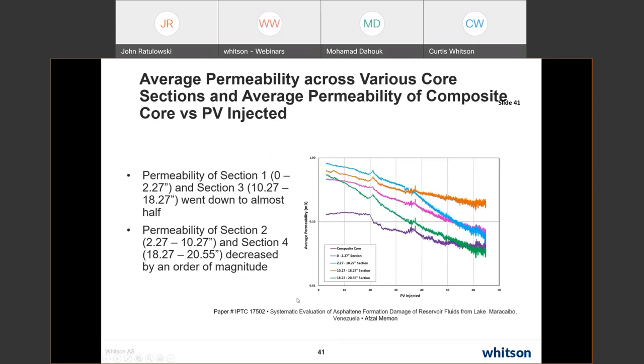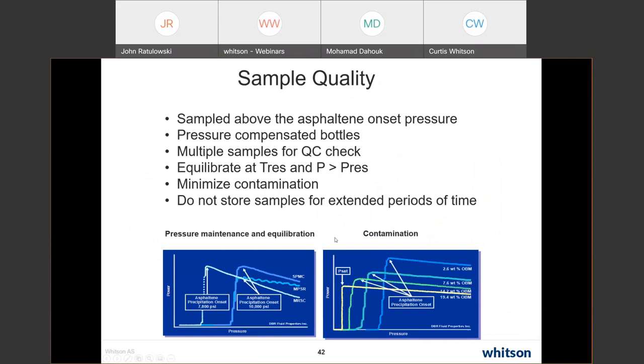This was a set of experiments that actually worked pretty well. It was done on a fluid from Lake Maracaibo, Venezuela, where we knew that the wells actually did have impairment, and we could see the impairment in the core flood. In areas where we were getting precipitation, the pressure region where we were getting precipitation, and these would be areas like section 2 and section 4, we saw a large decrease in the permeability. In areas where we had high permeability, the permeability was not decreased as much, and that was kind of what we expected.